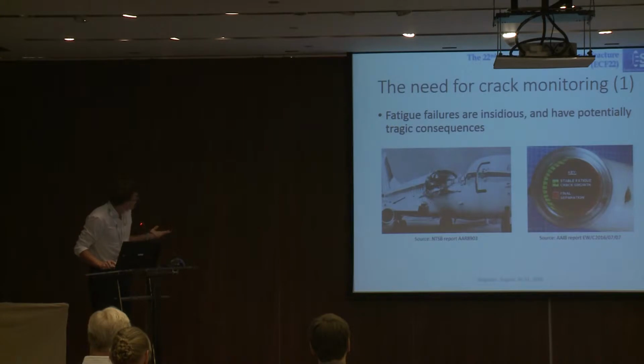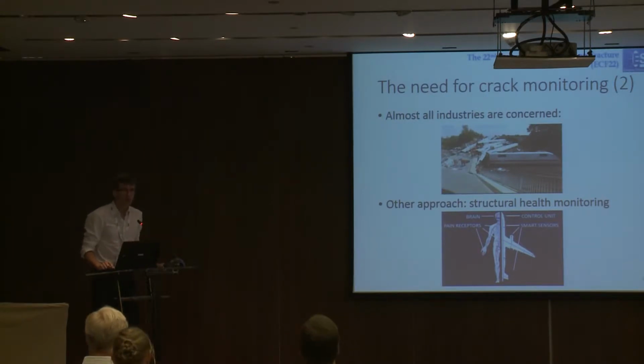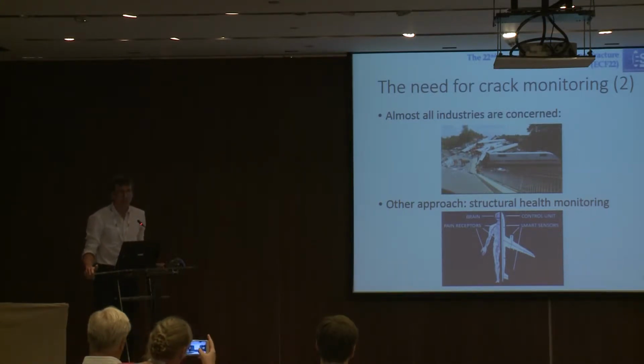And both of these aircraft were actually followed by a strict maintenance scheme which was respected, and obviously classical maintenance was unable to prevent the failure. I'm an aeronautical engineer, so I've taken pictures from the aeronautical industry. But of course, I think all industries are concerned by fatigue cracks. Here is another example of a quite dramatic accident, where there were more than 100 deaths. It was a German high-speed train that derailed while driving at maximum speed, which is of course not the best moment to have a derailment. This derailment was due to a broken wheel, caused by a fatigue crack that was not detected.